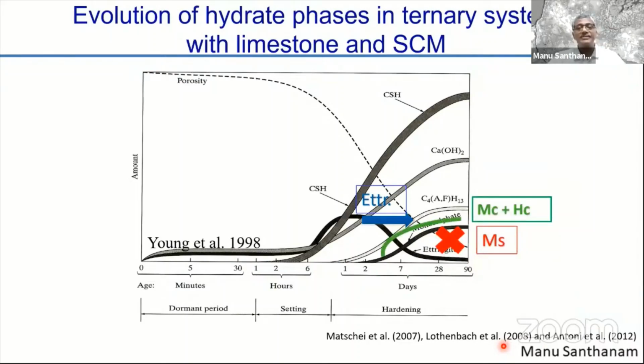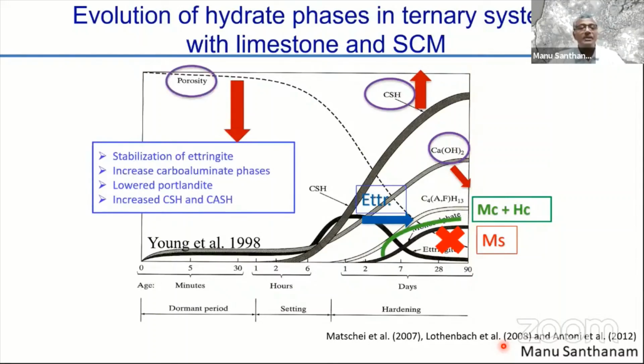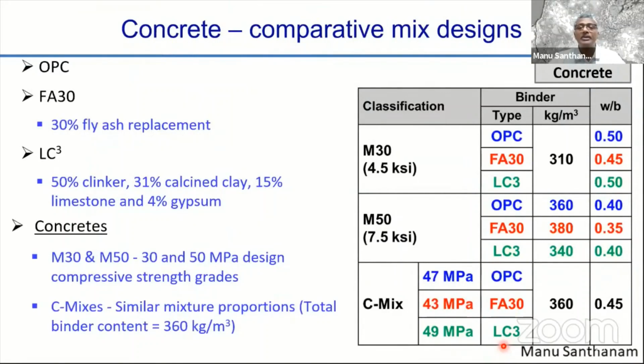This produces additional phases called monocarbonate and hemicarbonate, which start occupying the available pore spaces. It leads to an overall reduction in calcium hydroxide to produce additional CSH, or in these cases, what we call calcium aluminosilicate hydrate, because we are using a pozzolanic material in addition to limestone. So overall, the porosity reduces and the strength and durability are expected to increase.